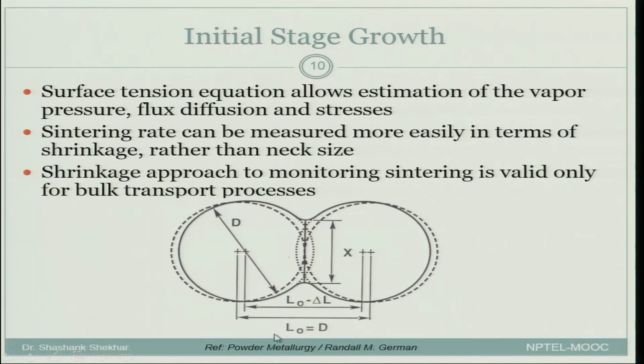For example, you start with L naught and after sintering the center to center distance is L naught minus delta L. So, this delta L represents the shrinkage in terms of center to center distance. Shrinkage approach to monitoring sintering is valid only for bulk transport processes.